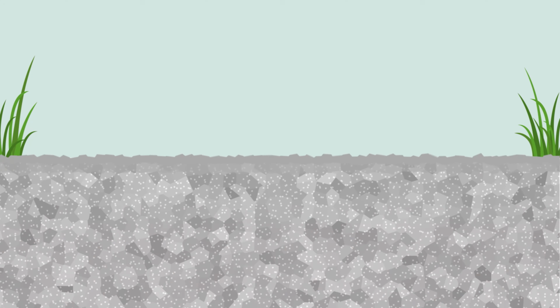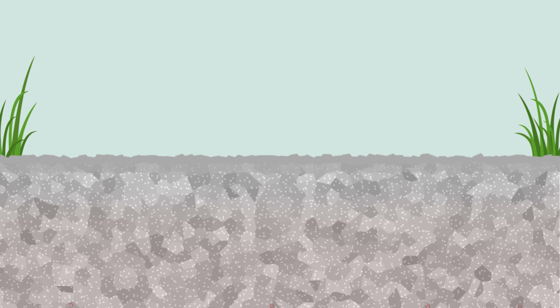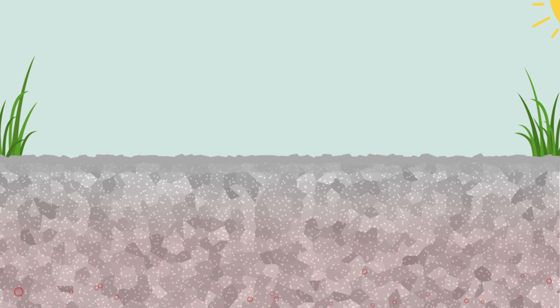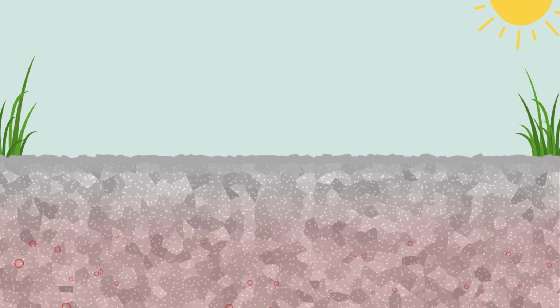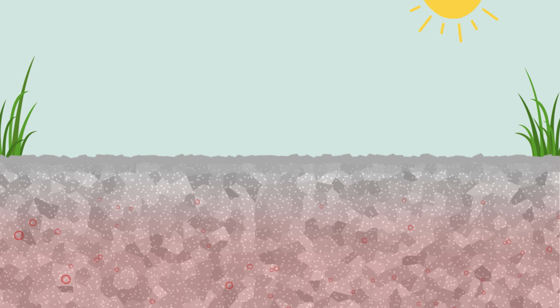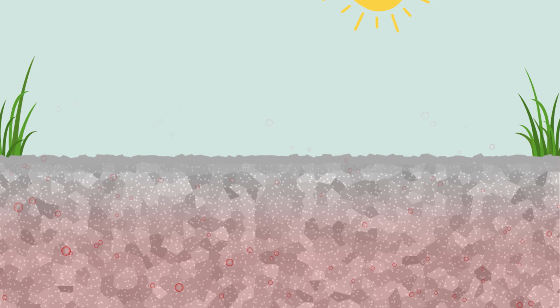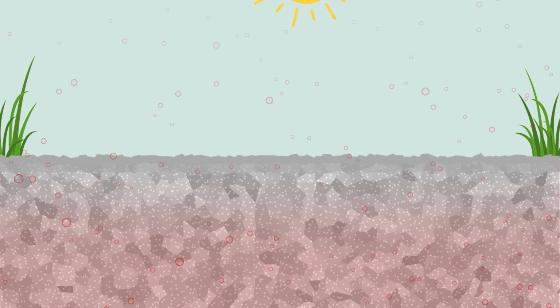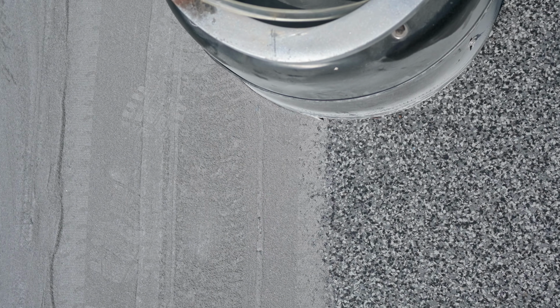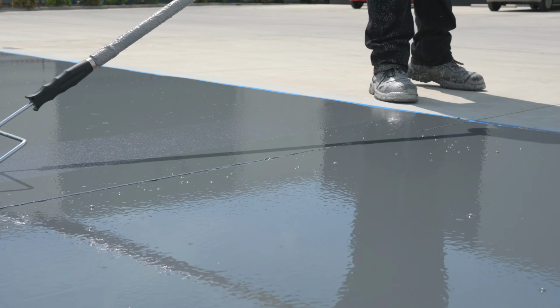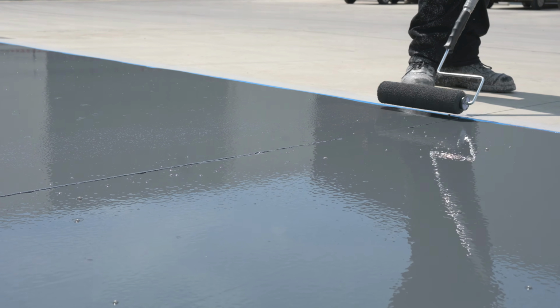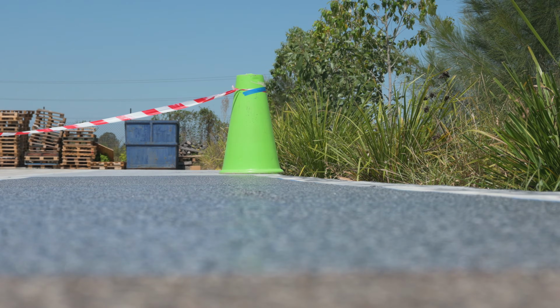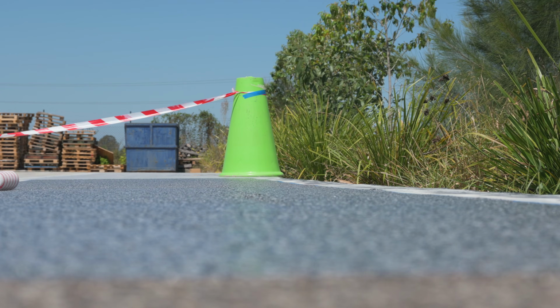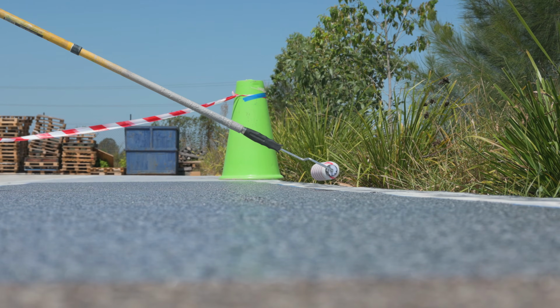As you might have guessed, bubbles form from the outgassing of a concrete slab. Outgassing is the slow escape of the pressurized air from the surface. The main reason behind outgassing is the rise in temperature from cold mornings to hot afternoons. This heating causes the air in the concrete to expand and thus blow out the concrete. Generally, slabs that are more porous tend to have the most issues, especially if applying your coating whilst the slab is still heating. Bubbles take away from how good the overall outcome of your application looks, which isn't ideal.